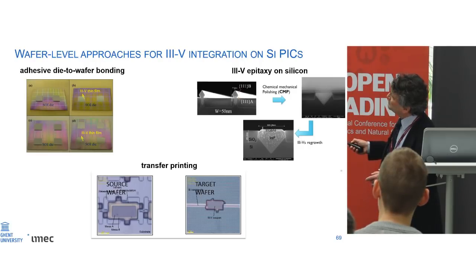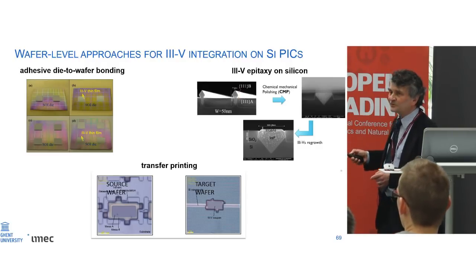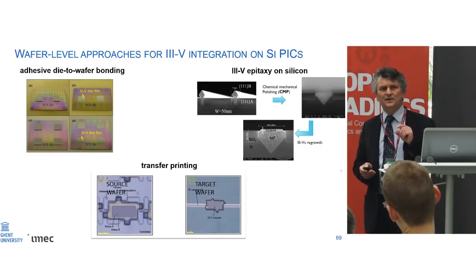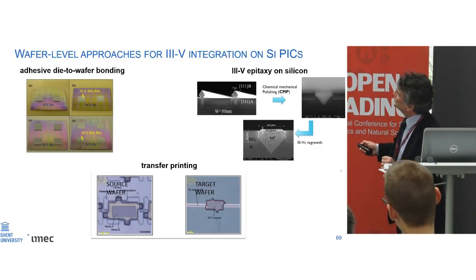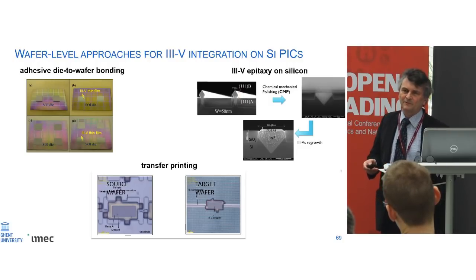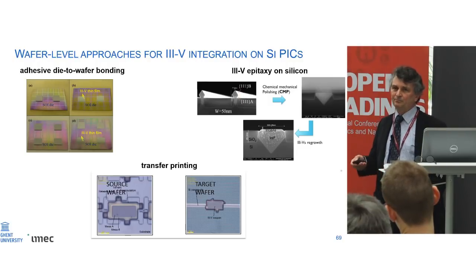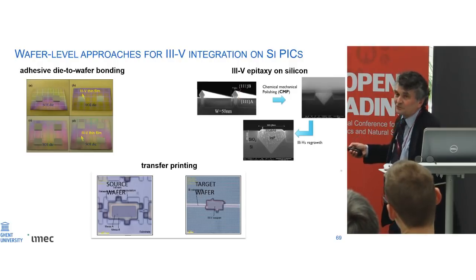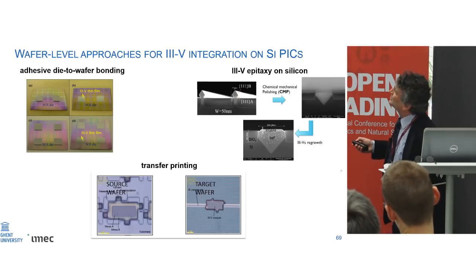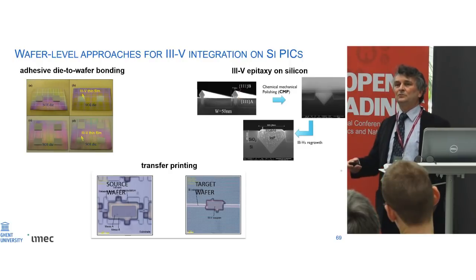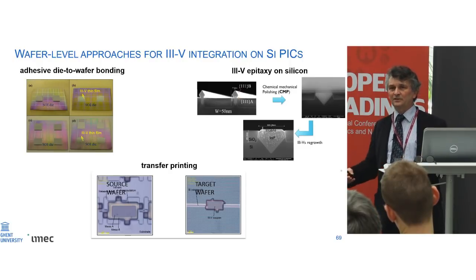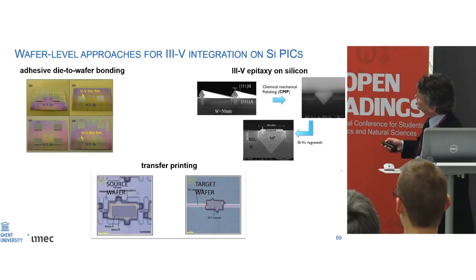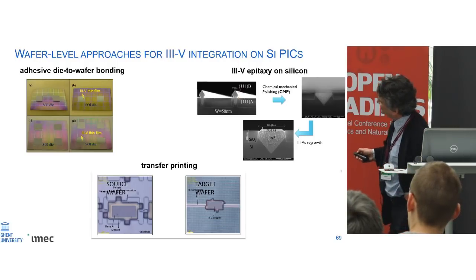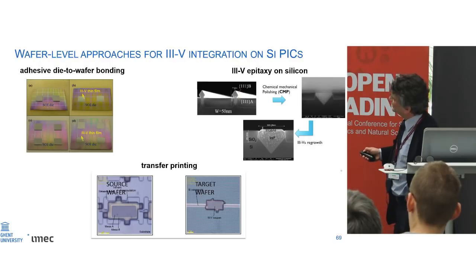After that, you remove most of the III-V substrate, down to the fact that what is left of the III-V is just the very thin epitaxial layer structure of perhaps a few micrometers thick. And with that structure, you go back to a wafer fab, and do all the patterning, because here the III-V is just epitaxy, just layers. And then you pattern it into waveguides with contacts and everything, into a laser, essentially. That's what people do. And a variation on the same theme is called transfer printing.